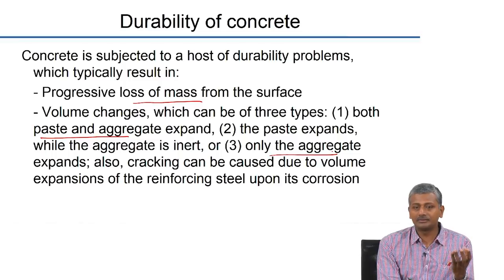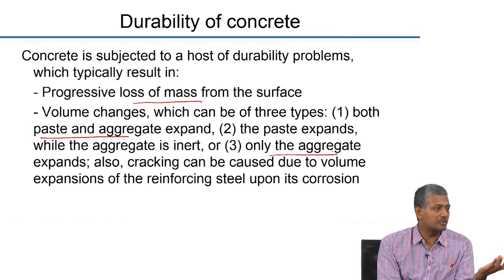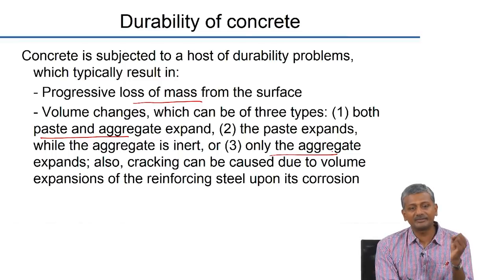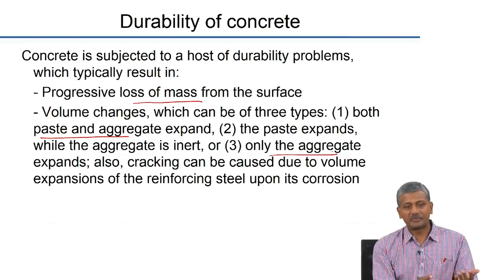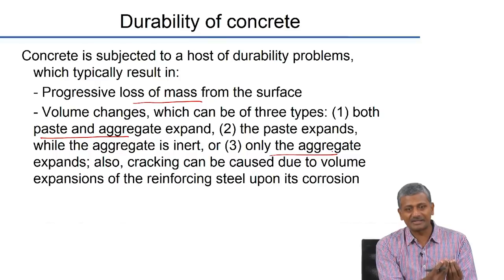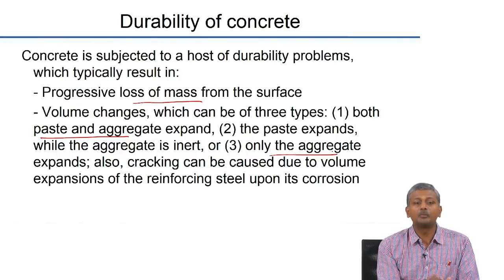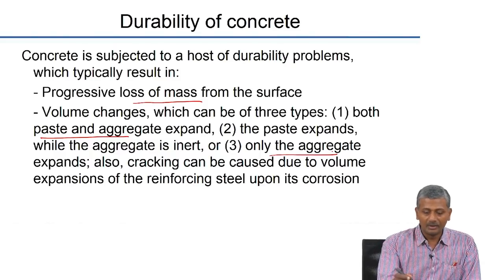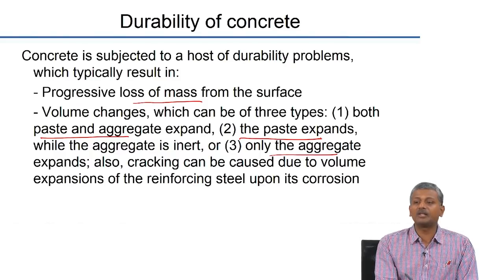Water inside the pores of the aggregate and the pores of the paste will freeze to convert to ice, and that will lead to expansive pressures, right? Well, yeah, expansion is happening for the whole concrete, but the paste itself can expand locally, the aggregate can expand locally depending upon the extent of porosity that is available in the aggregate.